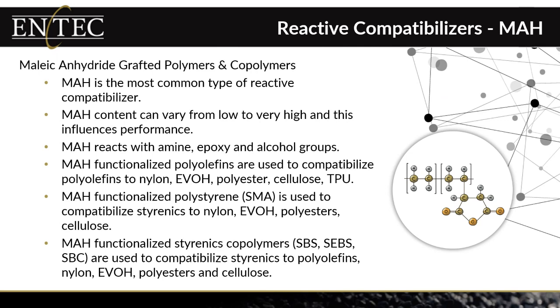The maleic anhydride tends to react with amines and epoxy and alcohol groups in the polymer. And many of these maleic anhydride functionalized materials are based on polyolefin backbones. They're also based on styrenic backbones, and in theory, we can functionalize many different polymer families. It's just that the polyolefins are probably the most common. In addition to that, there's polystyrene products that are functionalized with maleic anhydride. And what we're doing here with the polyolefins is typically compatibilizing a polyolefin like polyethylene or polypropylene to polar materials like nylon, EVOH, polyester, cellulose, etc.